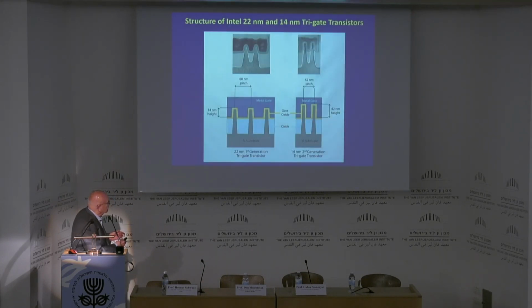It looks like this. It's a fantastic device, but in order to do nothing but electron transport, it heats up, and you have to put a coating on it which allows it to stay at a uniform temperature, which is usually hafnium oxide or titanium nitride, something like that. So it's a passive coating which also prevents the defects moving in the transistors such that it works for decades, basically without decomposition or deterioration.